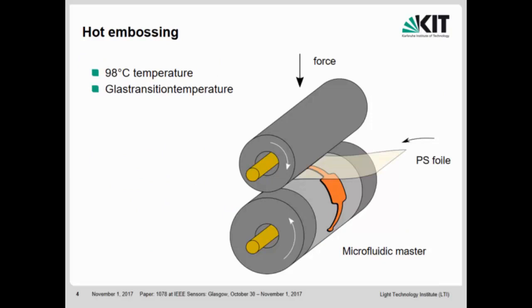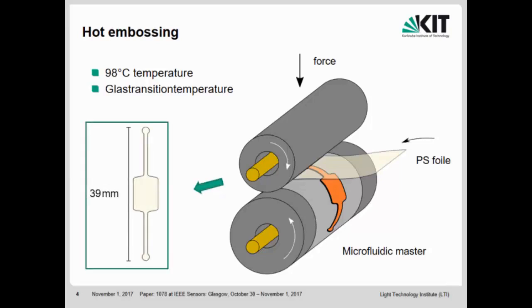And the fabrication of our chips will be done in a roll-to-roll manner. So we have a hot embossing tool based on a roll-to-roll fabrication scheme. We have a master structure for the microfluidic channel that we'll imprint into the polystyrene foil. So we'll heat the whole thing up to above the glass transition temperature of the polystyrene, and then squeeze it through, apply a certain pressure, and we'll end up with these microfluidic channels with an inlet and an outlet and a test chamber where we can print different things in the middle.